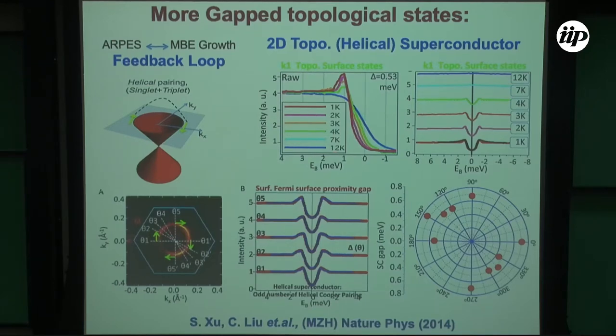In this case, the Tc is around 7 Kelvin. Now you can say when you're at 12 Kelvin, the normal state at very low energies near a millivolt, you have a Fermi step, there's nothing. And this Fermi state is coming from the Dirac state. And then as you lower the temperature, things get redder and redder. Look at 1 Kelvin. Clearly, there is a gap. Using the Fermi step, you line up the Fermi level. And then you can see a gap has developed, and there's a coherence peak, right? And this gap you can measure by looking at the ARPES data, you see that the gap is about 0.5 millivolts, right? And based on the gap size, you can also estimate the Tc, which gives you something around 7 Kelvin. So in other words, there's internal consistency.